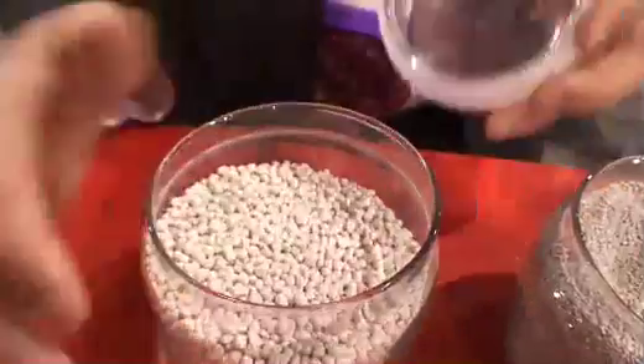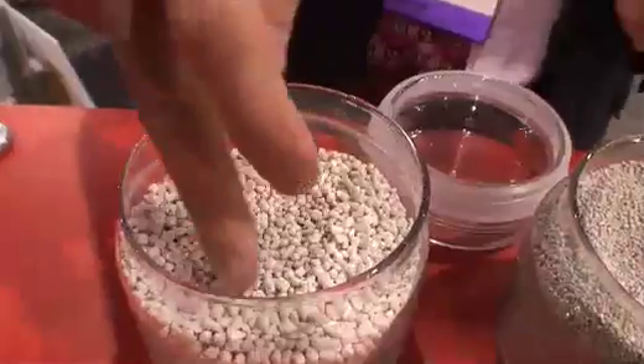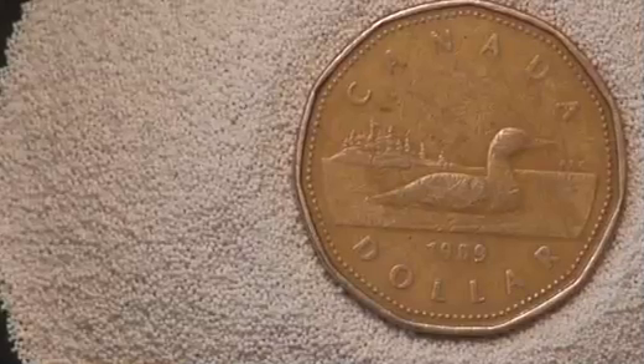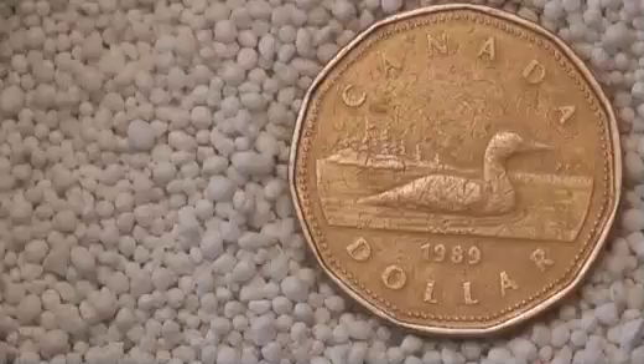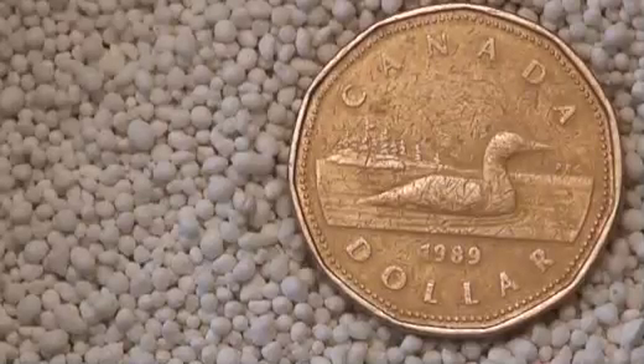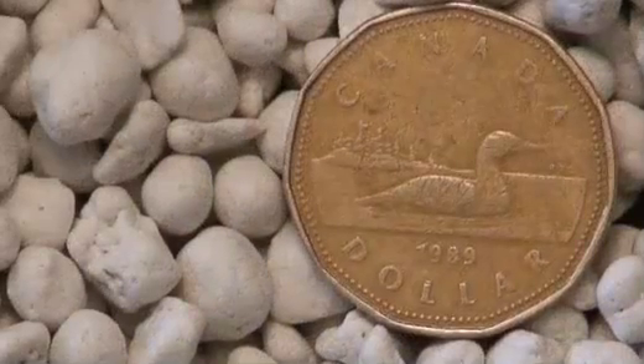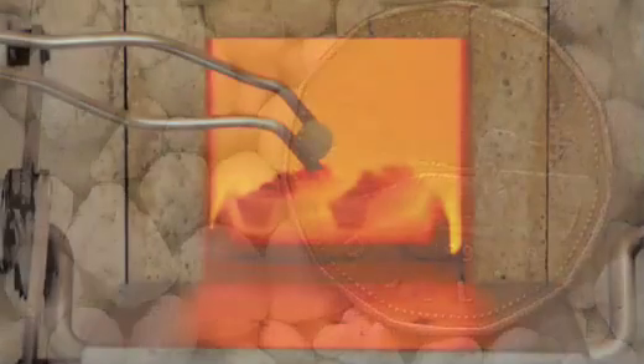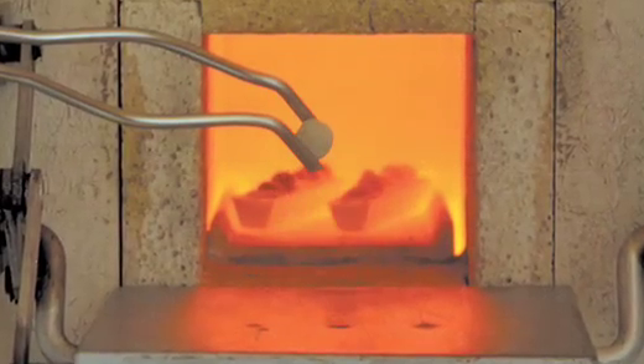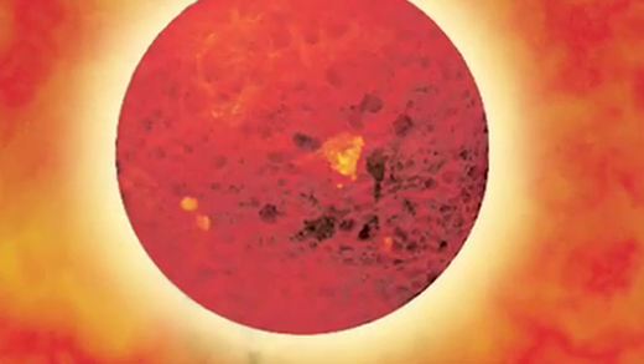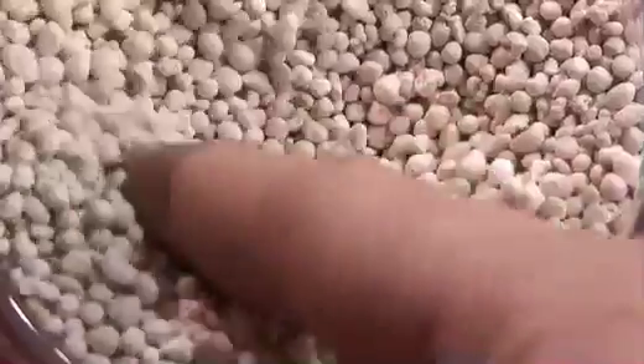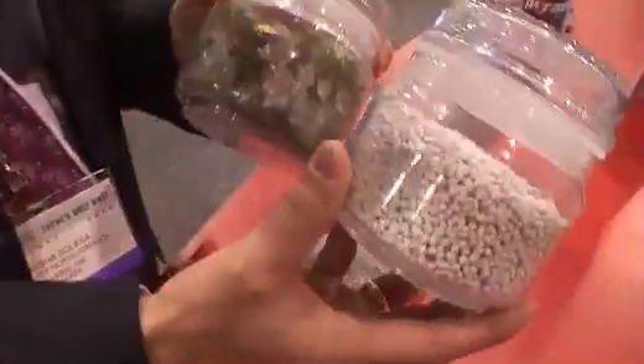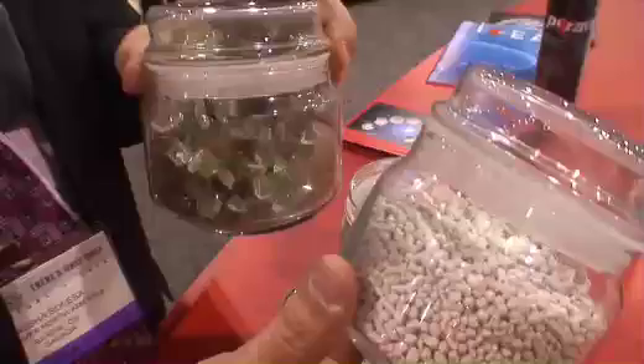This is the final product. Has a very high compressive strength. Again, we go from 10 pounds per cubic foot density up to about 30 pounds per cubic foot density, and that is obviously the smallest size, which is 100 to 300 microns, and we go up to 4 to 8 millimeter in diameter. It is blown up at 850 degrees Celsius, and it has a very short residence time in the kilns. So we can manufacture over 30,000 metric tons a year at our plant currently. And what you're looking at is the final product, which came from recycled glass.